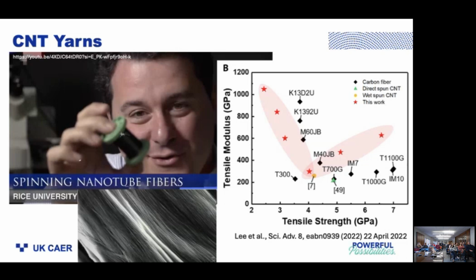But the Pasquali group at Rice University has pioneered a lot of this. This was licensed by the Teijin Japanese fiber corporation to spin nanotube yarns from superacids, much like Kevlar fiber is produced, which is, I think, why Teijin was interested in it. The resultant properties are pretty remarkable. If you check out the red stars, really high modulus, really high strength. Definitely competing property-wise with existing state-of-the-art carbon fibers. Again, no oxidation, no carbonization. Pretty attractive. So we'll see where this technology goes.